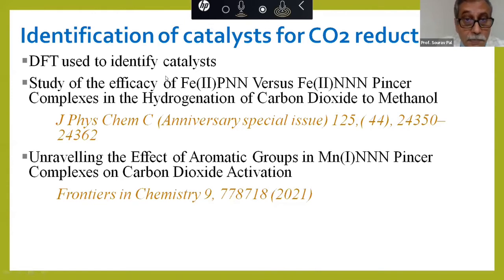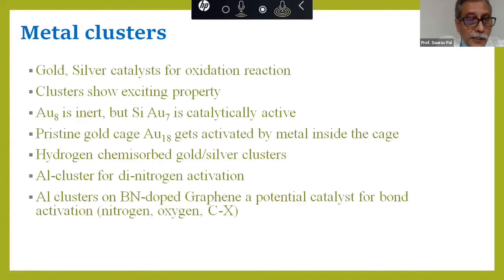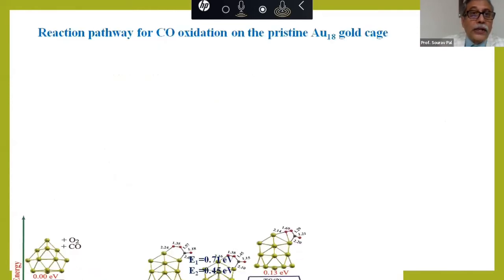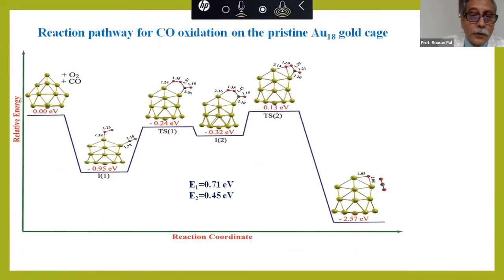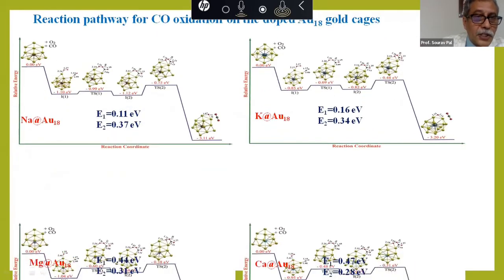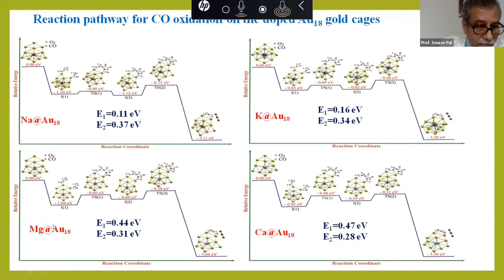So these, we believe, are complexes which have a lot of promise and which we would like to take forward. We have been working on metal clusters, I already told you, and some of the examples I just want to give you. For example, if you have a gold cluster Au18, this is a pristine gold cluster, and we are looking at a CO oxidation reaction, you can look at the transition barriers. They're quite high. And as soon as you put metal dopants, like sodium, potassium on the same gold cage, magnesium or calcium, all the activation barriers go down.